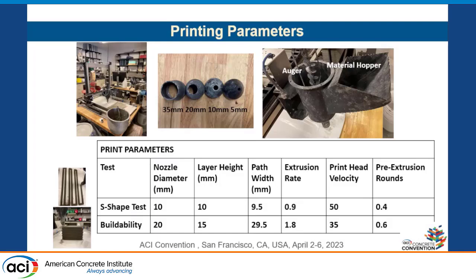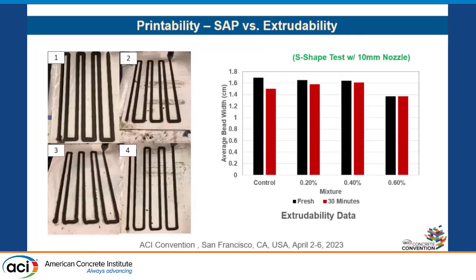So what we had to do later was to go through the printing of this 3D printable mixture with different parameters. We did the extrudability test and also the buildability test at constant printing parameters, but different nozzle diameters. For extrudability, we use a 10 millimeter nozzle, and for buildability, we use a 20 millimeter nozzle. But the rest of the printing parameters were kept constant. So the first issue was about the extrudability.